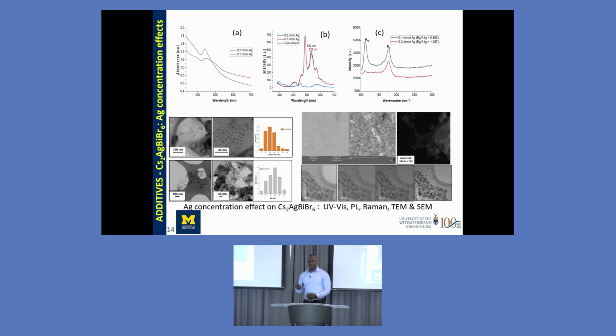The higher electron beam normally should degrade or damage the material within few seconds. But in our specific case, because the material was very stable, they could resist until 1 minute, 5 minutes, 10 minutes. But at 20 minutes, we could now see that there was some degradation that could be observed, because we could see the small atoms of silver being shown all over the image, confirming that indeed there's a degradation of the mixture that we formed, which is cesium silver bismuth bromide.